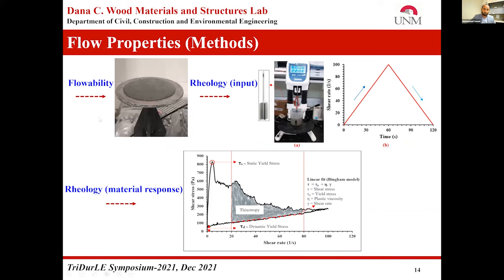To consider this, we assessed the flowability using a flow table, and rheology was measured using a Brookfield rheometer. The rheology evolution over time was assessed at 0, 15, 30, 45, and 60 minutes. A hysteresis loop technique was used, and when we apply the shear rate, the material response, that is static yield stress, dynamic yield stress, plastic viscosity, and thixotropy, was measured, considering the material as a Bingham material.